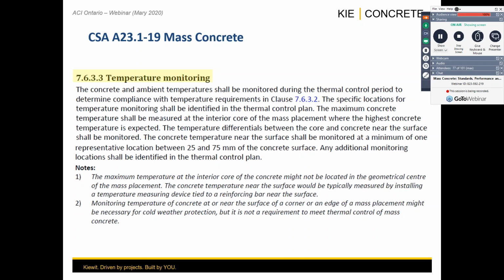But typically, you're going to have sensors at the maximum core, where the maximum temperature is going to occur, and you're also going to have sensors on the outside. And the outside meaning on the rebar that is closer to the surface. Sensors are going to have to be secured. The standard allows to have it between 25 and 75 millimeters.